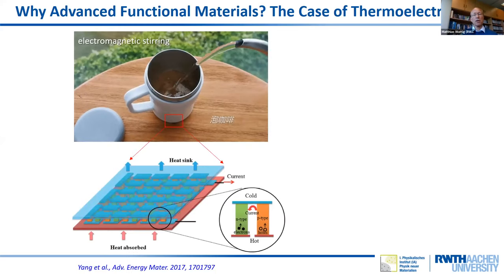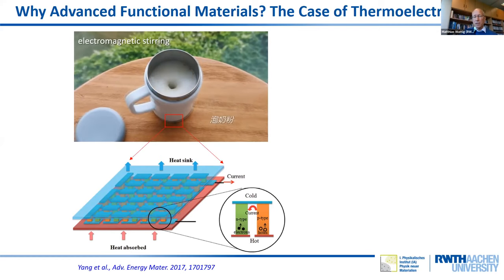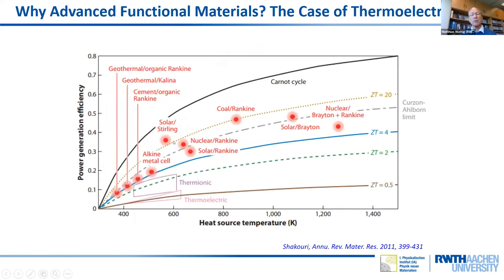Now, the concept behind thermoelectricity is pretty simple. In principle, you only have to advance the figure of merit, ZT, which depends upon the Seebeck coefficient, the thermal and the electrical conductivity. This is how this figure of merit looks. The best possible thermoelectric materials now have ZT factors of the order of 2. And you would definitely like to raise ZT up to values around 4. But even with a value of ZT of the order of 2, you already can do pretty cool things,